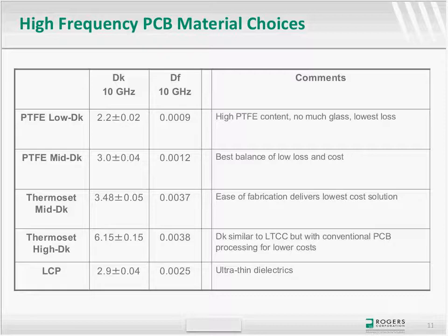Also, PTFE itself can go through a significant change in dielectric constant versus temperature. So sometimes in environments that have a lot of fluctuation in temperature, these materials by themselves may not be the ideal solution, but they do, like we said, offer very, very low loss. And because of the high PTFE content, they tend to be higher priced materials out of the products that are here in this presentation.